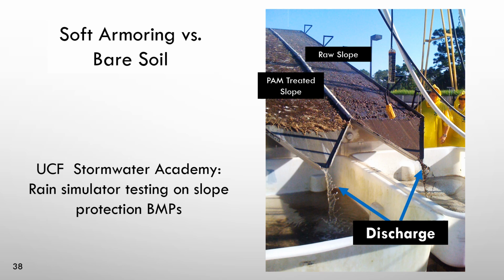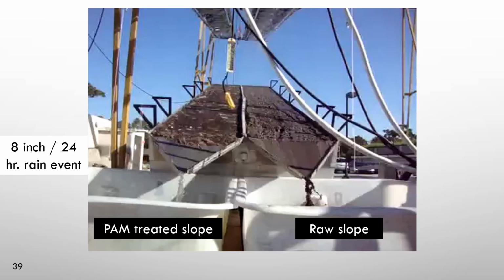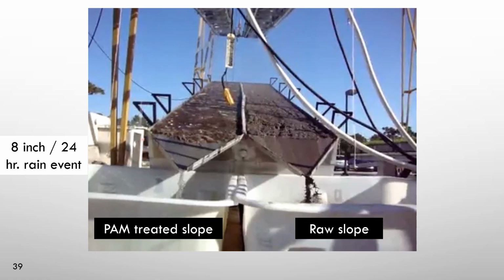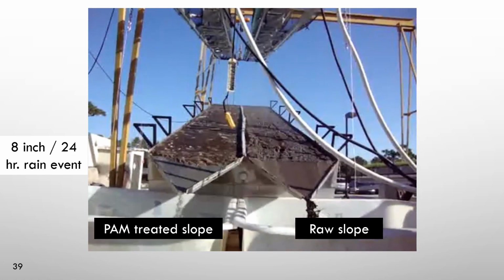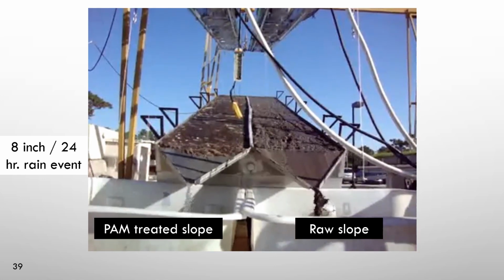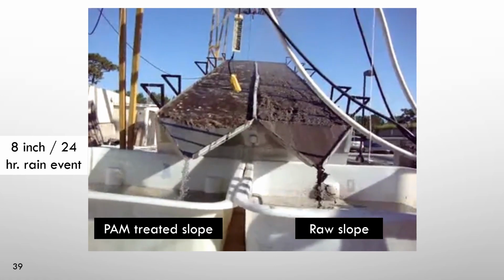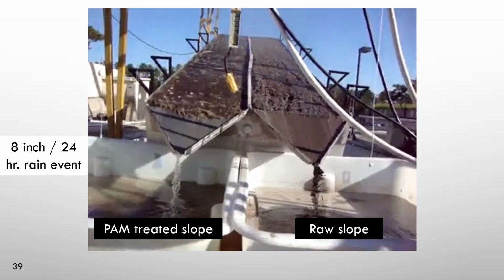And again, the erosion control matting was keeping a lot of the erosion from occurring, but we still had very high turbidity running off because of some of the fine particles in that soil. On the PAM treated slope on the left, we're preventing the erosion and then also improving the water clarity. So they did an 8 inch / 24 hr. rain event, and you can see the raw slope on the right. There's erosion, there's very, very high sediment running off that slope. And on the left-hand side, it's relatively clear water.